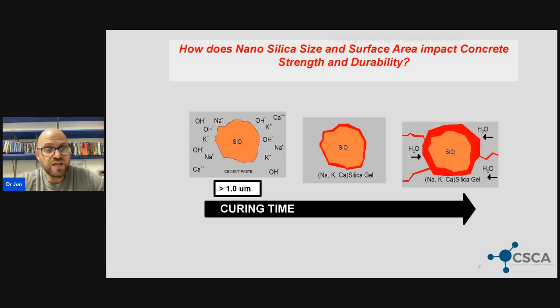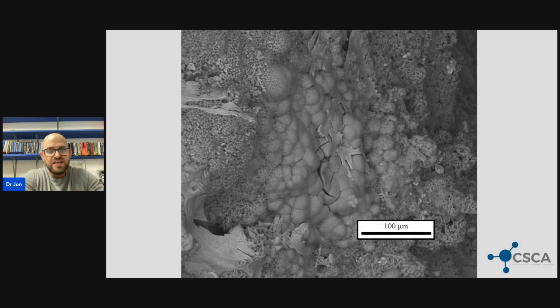As more water is imbibed into that hydrogel, and that hydrogel expands from a hydrogel to almost like a superabsorbent polymer, there's a residual stress induced in that confined zone. And at a certain point, that residual stress overcomes the shear and tensile capacity of our hydrated cement matrix, and in some cases our aggregate, cracking the concrete, inducing more water and salt flow. It's just a vicious, nasty cycle.